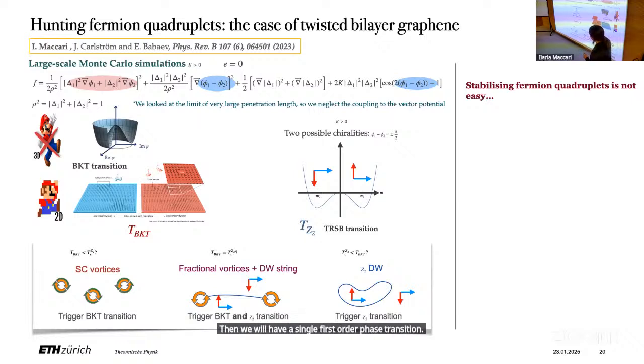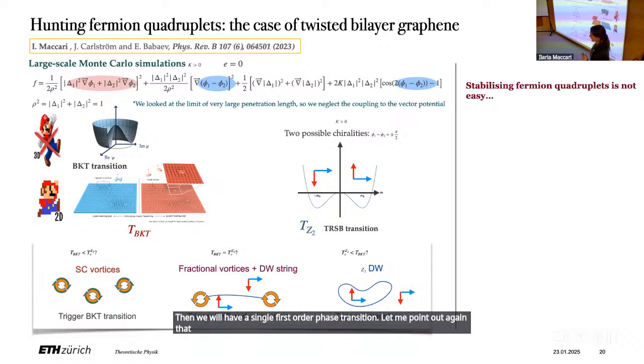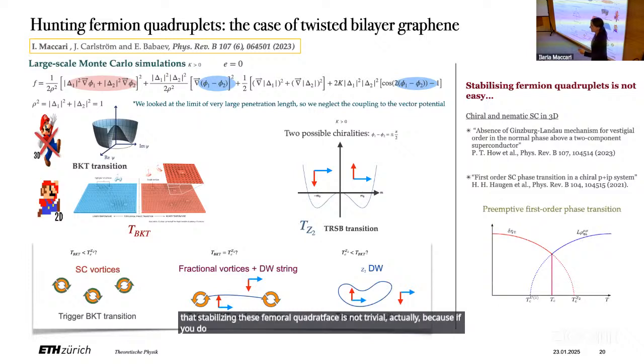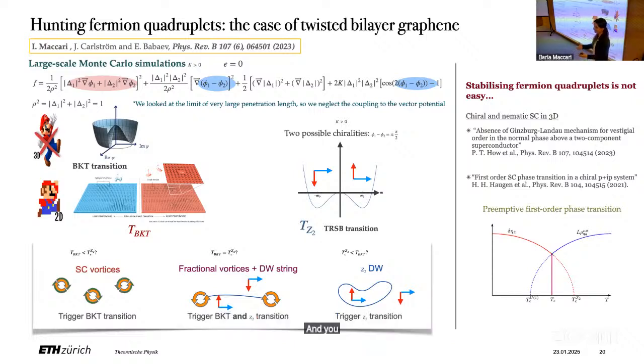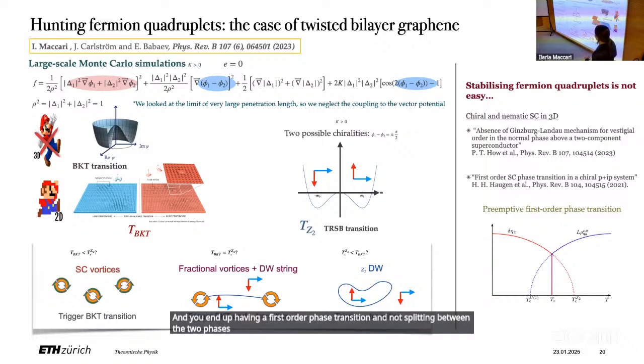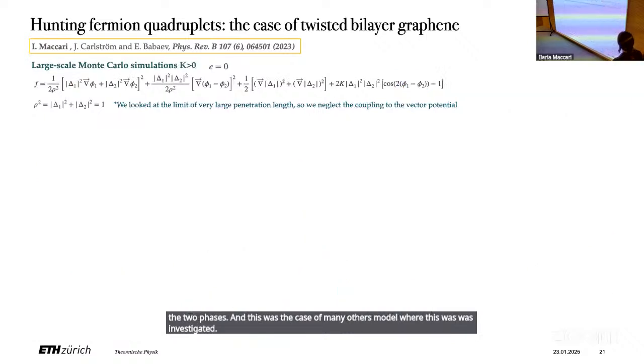Let me point out again that stabilizing this fermion quadruplet phase is not trivial, because if you do the calculation properly and account properly for the interaction between different topological defects, very often the proliferation of one object triggers the proliferation of the other topological defect, and you end up having a first order phase transition and not a splitting between the two phases. And this was the case of many other models where this was investigated. In our case, what we found is the following.